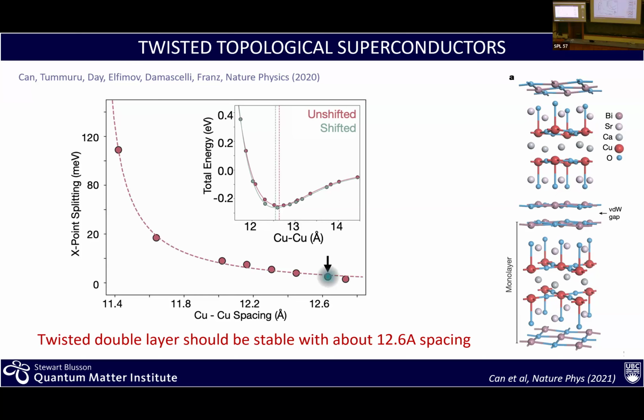It's some kind of a texture in momentum space. At least that's what the theory predicted. So you're going to see that exact situation, where the positive phase will overlap with the negative phase, in the next slide. But basically, you're inducing that by really the interaction between those two. If you didn't have that, it's large enough to overcome what you want.